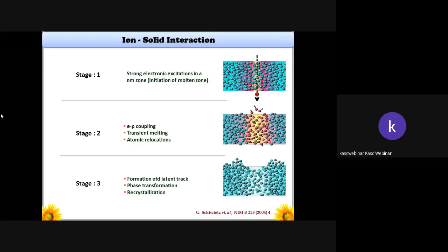Then further we can categorize into different steps how it is possible to achieve recrystallization or phase transformation by using this ion solid interaction. In step 1, if an incident energy is deposited over the surface of a sample, very strong electromagnetic or electronic excitations occur in a nanometer level zone. Actually, it may create the initial part of a melting zone.